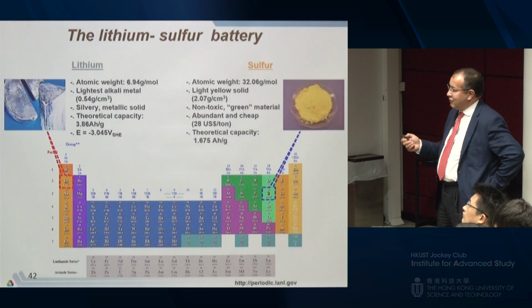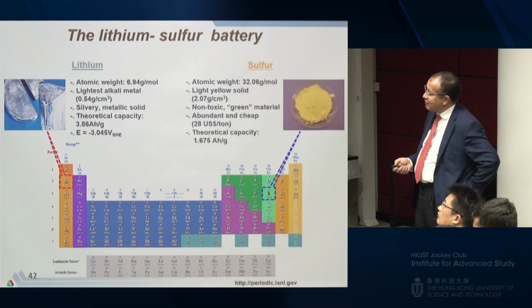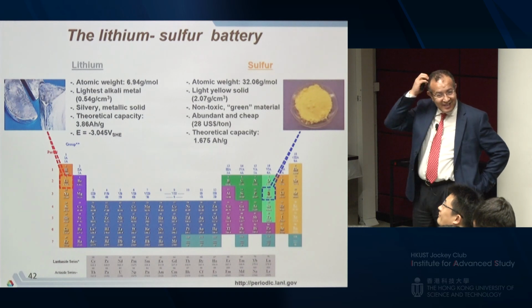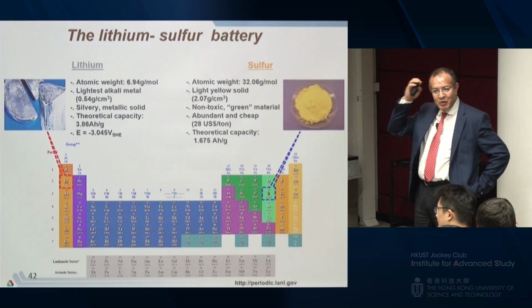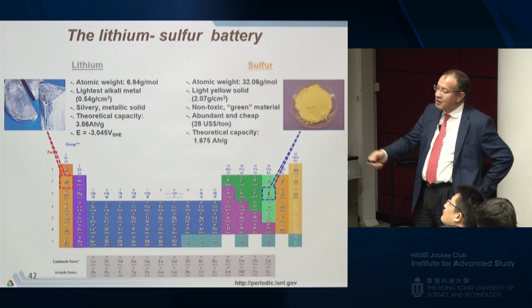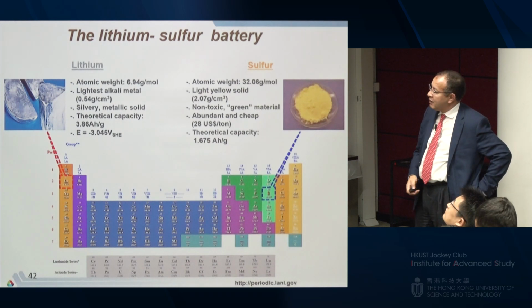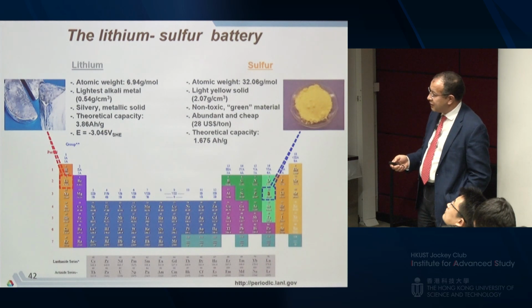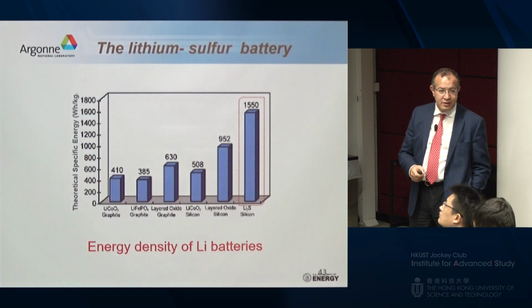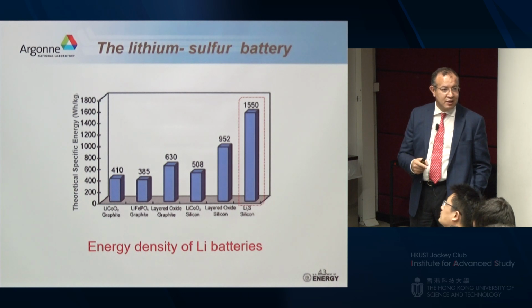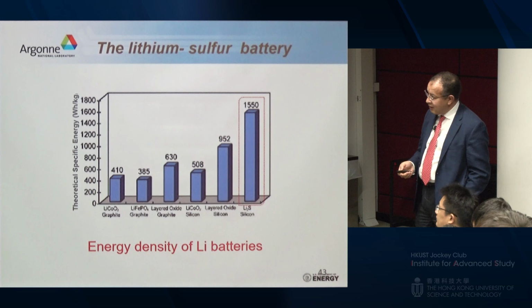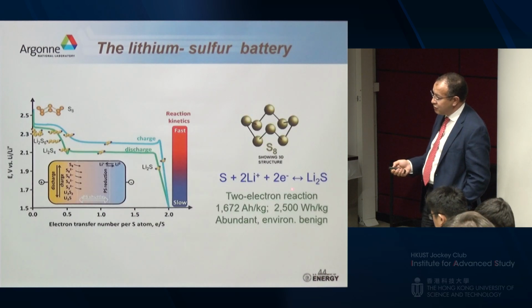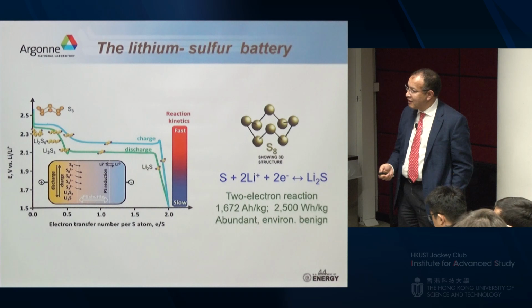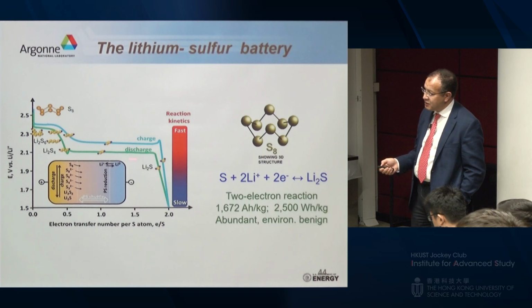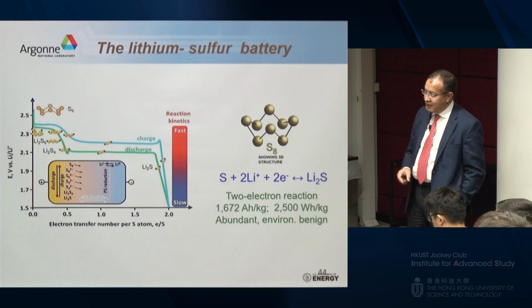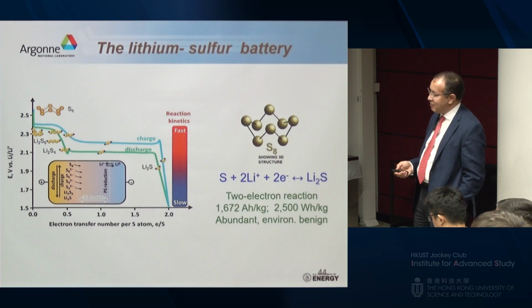Okay, why sulfur? Sulfur obviously is dirt cheap. I think you can buy it for $28 a ton. As a matter of fact, if you go to Saudi Arabia, they have mountains of it because it's a byproduct of the petroleum industry. That's one reason. And the other reason is it has very high gravimetric energy density, 3 times lithium-ion. Not only cheap, but it gives you 3 times more energy. And one of the reasons why it gives you that much energy is because it's a 2 electron reaction, not 1. During the discharge, you have multiple phases, polysulfide that is formed. And that's a problem. I'm going to summarize all these issues here.